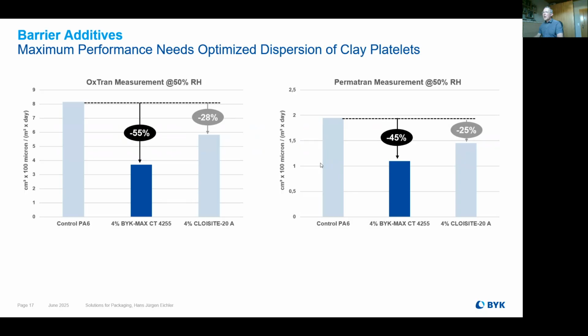If we look now at the important part, what does it mean if we speak about oxygen or permeation increasing in barrier properties, you get here figures with 4% of one grade, which is called BYK-MAX CT4255, or 4% of Cloisite 20A. And you see with this performance of the CT4255, which exactly fits from the organic modification to the polyamide, we are able to reduce the oxygen permeation down to 55%. With, I call it now, a wrong clay decision, you have only the chance to get 28 or nearly 30%. Same with the permeation of water vapor. You see with the right clay grade, the CT4255, a nice reduction of 45% compared to the, I call it now, wrong clay with 25%.